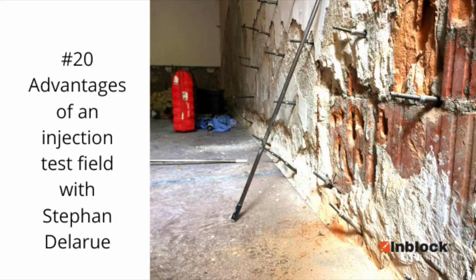And we had no clue how many honeycombs are inside. Is it a weak or a strong place? So we also placed some packers at different distances, and we injected a polyurethane resin, which is also a possible solution for strengthening with a high strength of the product. You can have a high strength of the material without any foaming factor. You can have a strength of, for example, 60 MPa, 60 Newton per square millimeter.